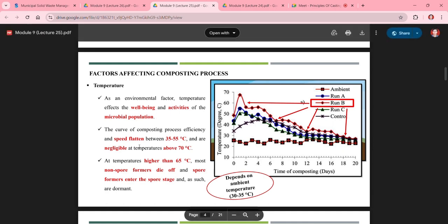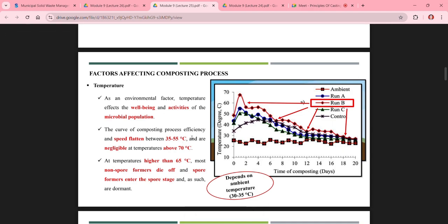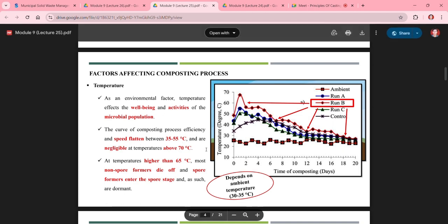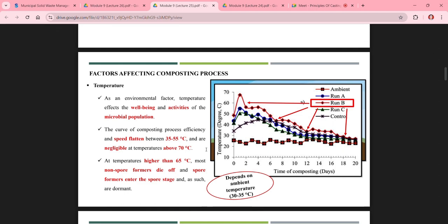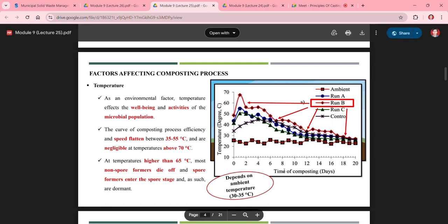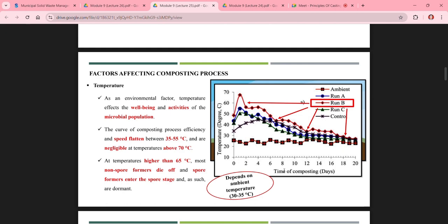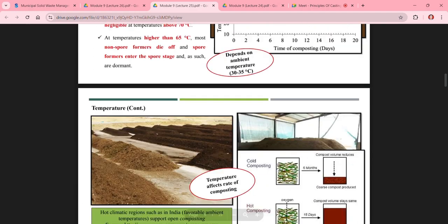The curve of composting process efficiency and speed flattens between 35 to 55 degrees Celsius and is negligible at temperatures above 70 degrees Celsius, because above 70 degrees Celsius your bacteria and fungi are not going to sustain, and these two are taking the major part during the composting process. At higher temperatures, around 65 degrees Celsius, most non-spore formers die off and spore formers enter the spore stage and as such are dormant. So your composting process will not be happening at around 70 or 75 degrees Celsius. You need a temperature around 60 to 65 degrees Celsius for a proper composting process.